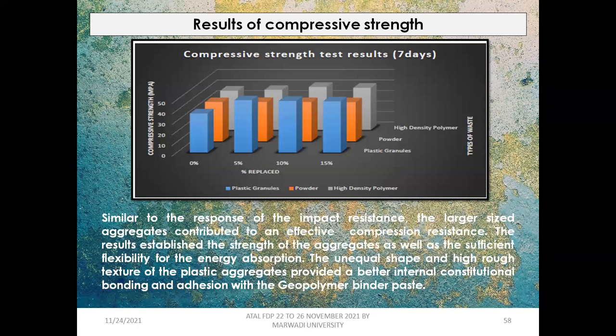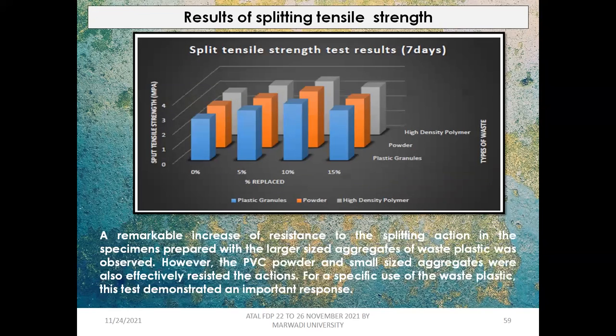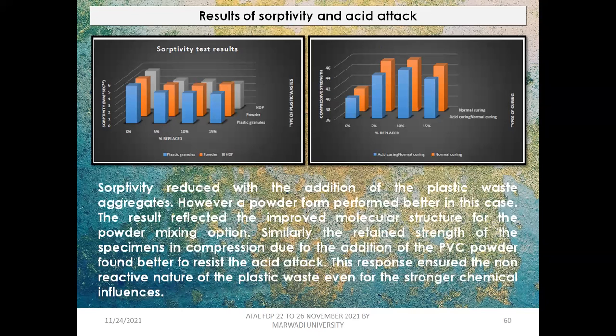These are the compressive strength test results with the replacement. Similarly, the tensile strength test results, and the sorptivity, which can also be cross-verified by adding this. And I must say that it retained the strength, and not only the strength, but also contributed to reduced ingress of water and chemicals inside.